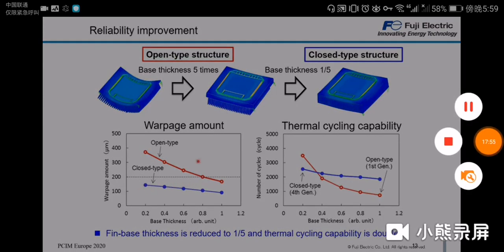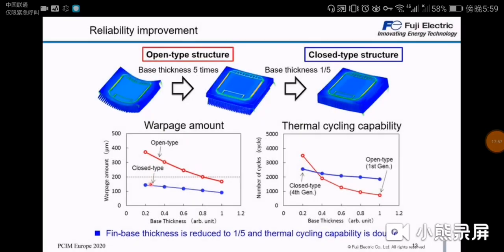And this means even looking at the graph at the bottom, even with this thin fin base thickness, we have very little warpage amount. Then on the right side, we come to the thermal cycling capability. The red graph is showing the first generation and the blue graph is showing the fourth generation. And as you can see, with a thicker fin base, if you move to the right on this graph, you will decrease the number of cycles that your module can withstand. However, with this open cooler structure, you need the fin base thickness in order to have a reliable module. With our fourth generation cooler, we can have a much thinner fin base while keeping a high number of cycles.